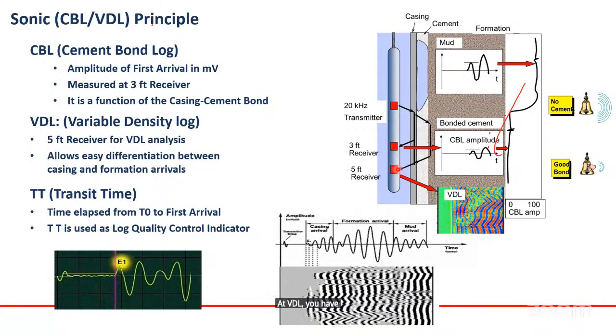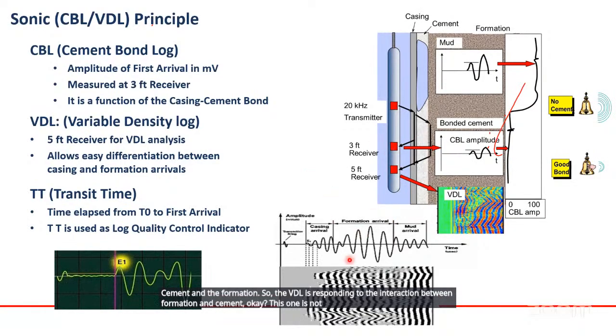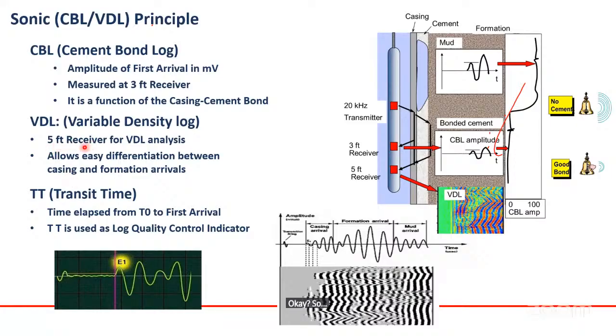VDL: you receive the signal at 5 feet, and also it goes through casing, cement, and formation. So the VDL responds to the interaction between formation and cement. Okay, this one is not amplitude. This one is a wavelet. So the 5 feet receiver is used for VDL analysis, which allows easy differentiation between casing and formation. As you see, this is what a VDL looks like. It looks like microseismic or seismic. So we have troughs and peaks, and we have black and white in between. If you have casing, you will have straight lines, but if you have the formation, it starts like this.